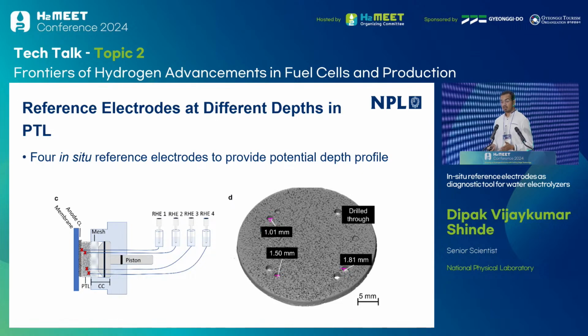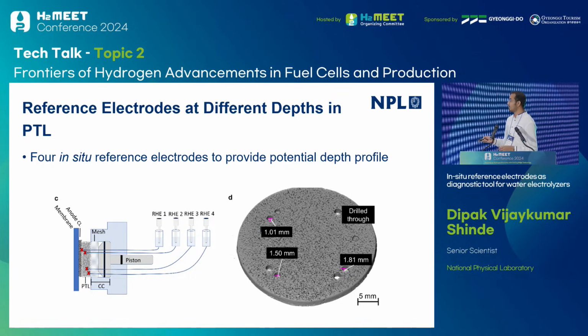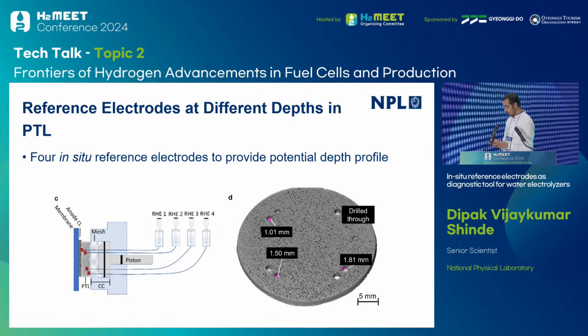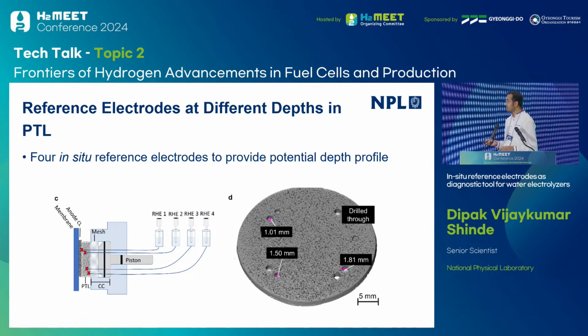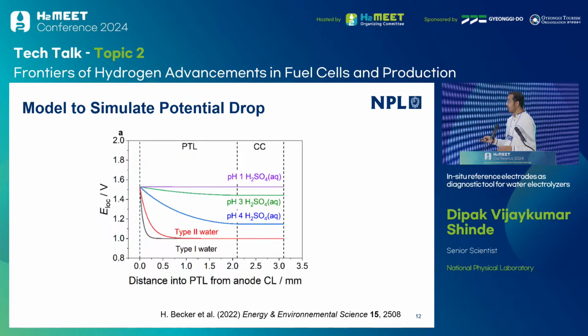We went one step further and we put more reference electrodes inside the porous transport layers at different depths, as shown here in one of the examples. And with this, we also developed a model to show that, typically proton exchange membrane water electrolyzers need pure water, so either it's type 1 or type 2 water. And this model shows that in type 1 and type 2 water, so this is a distance from your anode catalyst layer, as you move away from your anode catalyst layer, the voltage immediately drops to its open circuit potential, so it's no longer a corrosive environment for the materials.